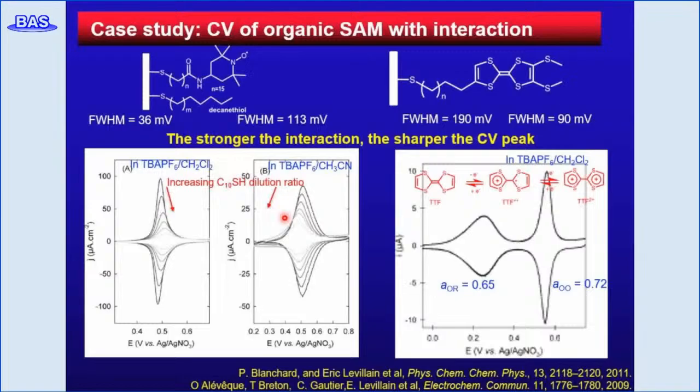These changes are contrary to the expectation, since the oxidation of nitroxy radical produces a positive charge, thus strengthening the intermolecular repulsions. However, at the electrode surface, ion pair formation and sorption changes in the electrode double layers that counteract intermolecular repulsion may play important roles.